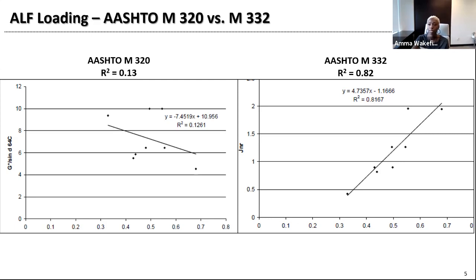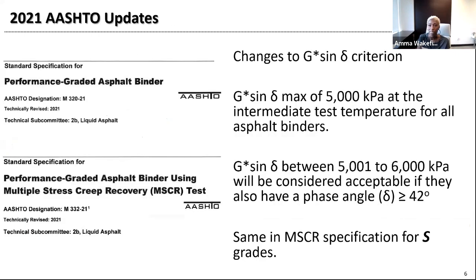And then on the right, it shows the same comparison, but it's using the JNR parameter from the MSCR test to compare with rutting. And you can see based on the R squared value, and R squared is a correlation that shows how well the two are correlating, and an R squared closer to 1 is better. So R squared for G star over sine delta is 0.13 when you round up, and R squared for the JNR was 0.82. So that's very good correlation, and further shows why we encourage the use of the MSCR specification.